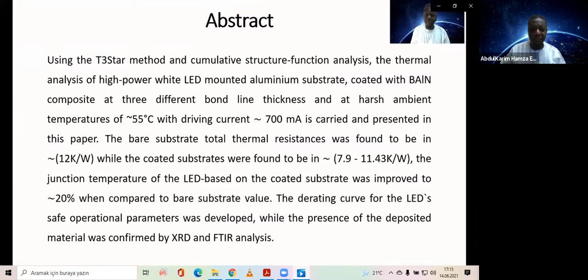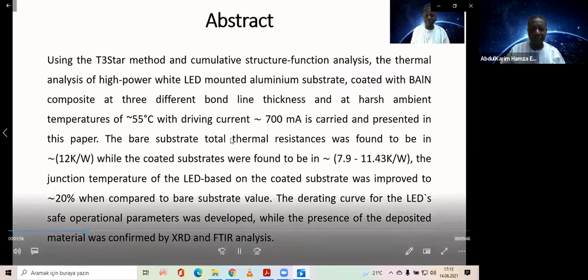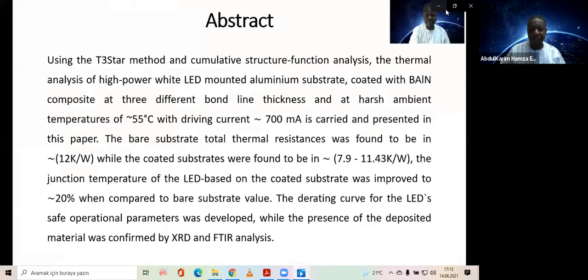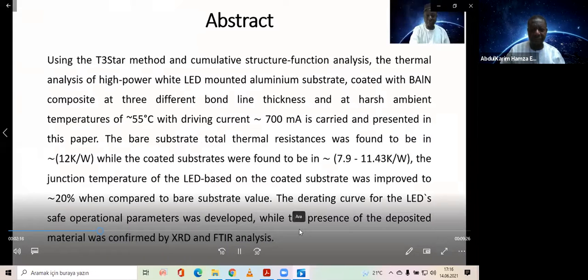The bare substrate thermal resistance was found to be in the range of 12 degree Kelvin per watt, while the coated substrate is found to have reduced the total thermal resistance of the LED package from 12 degree Kelvin per watt to 7.9 degree Kelvin per watt. And also the junction temperature is reduced by about 20% from the junction temperature with the bare substrate. The derating curve for the LED is also established using the Terra-LED view software, and the material presence is confirmed by XRD and FTIR analysis, as will be seen in the figures shown in the slides.